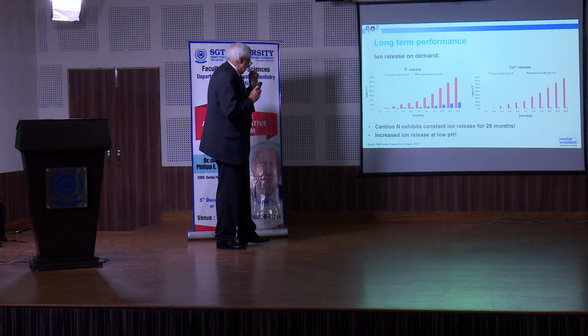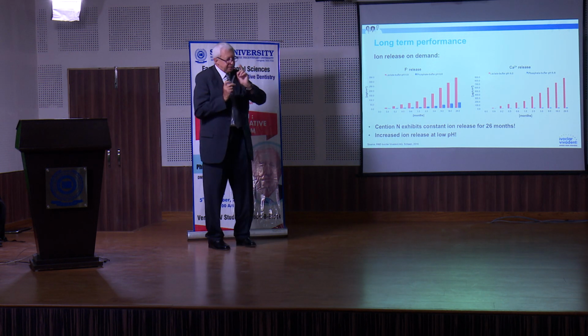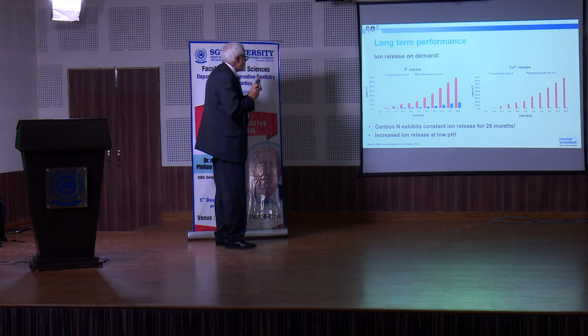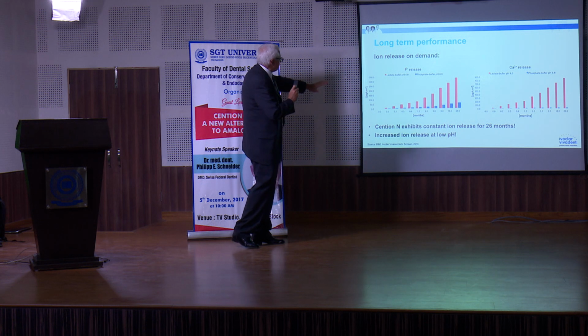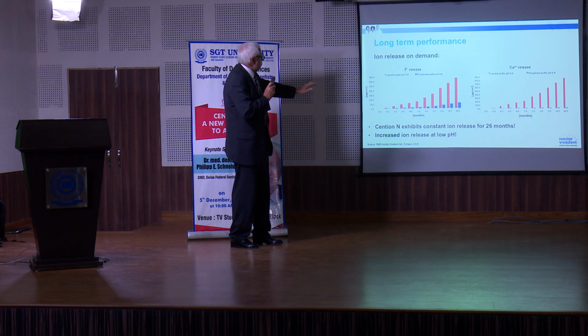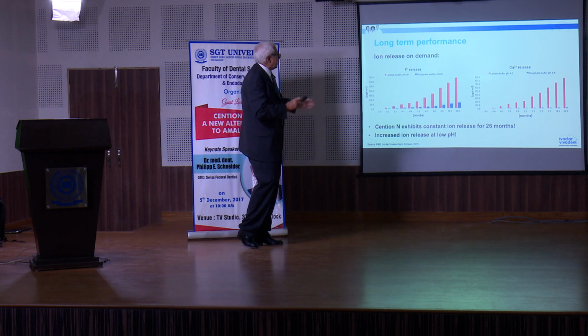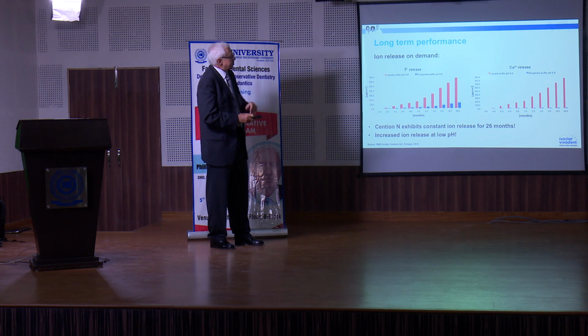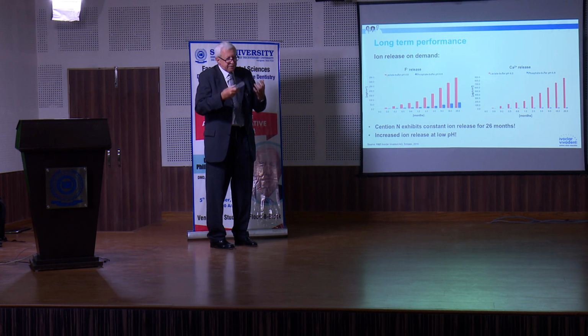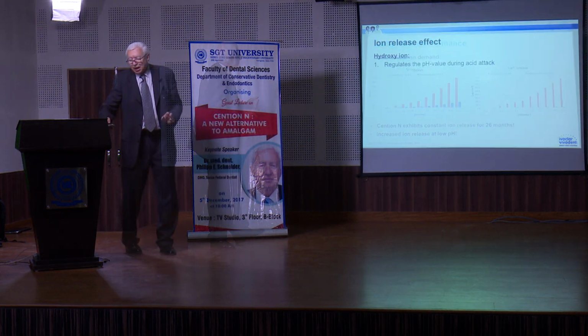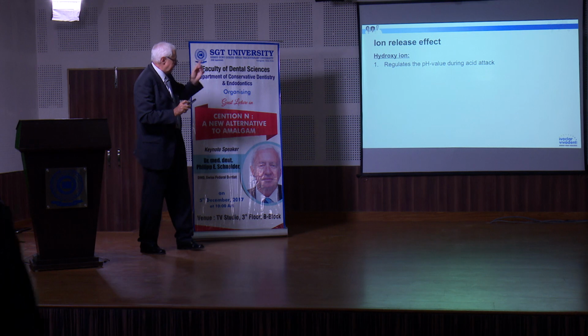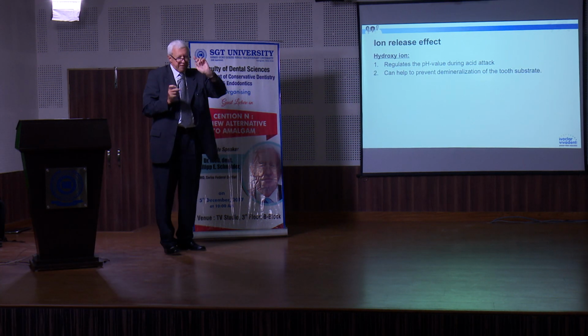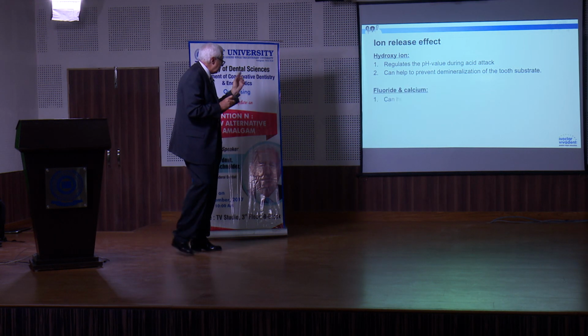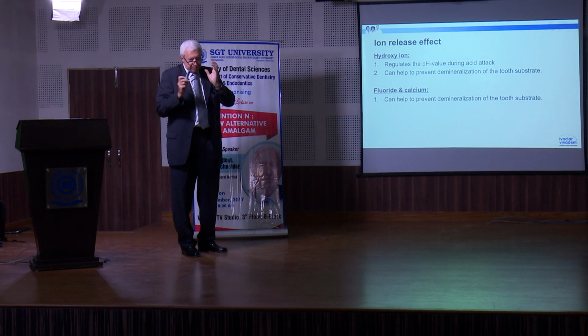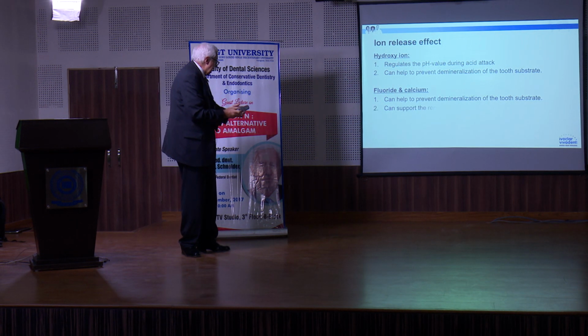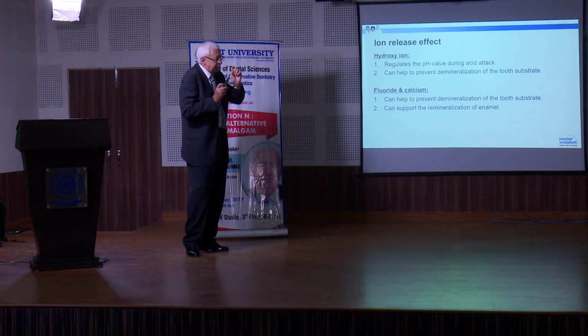And we have especially an increased ion release at low pH. At low pH, you see this in red. We have much more than in blue, when we have a phosphate buffer solution which goes in the direction of the alkaline side. So this is really ion release on demand. The ion release effect regulates the pH value during the acid attack. Then it can help to prevent the demineralization. On the other hand, fluoride and calcium also are preventing the demineralization, and we are setting the base for the remineralization.